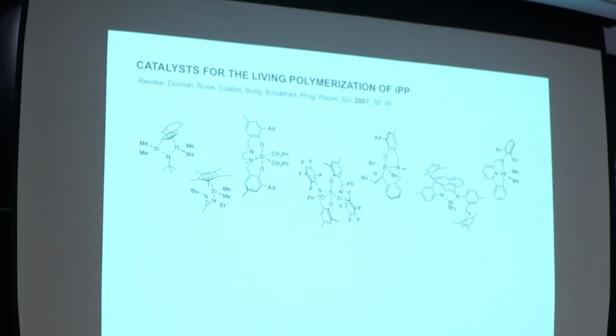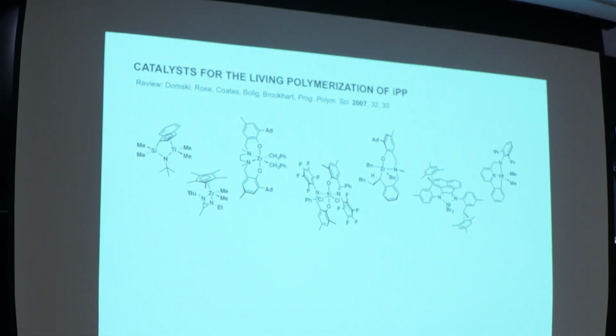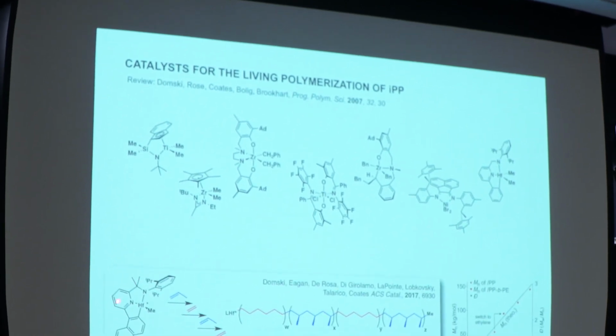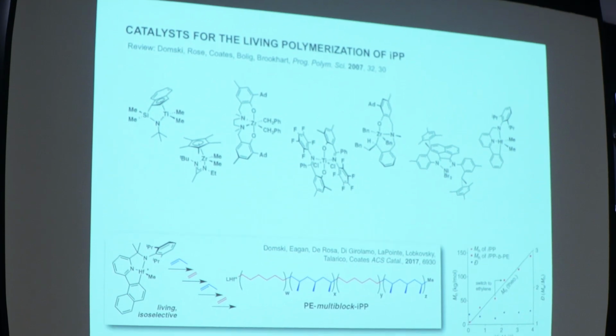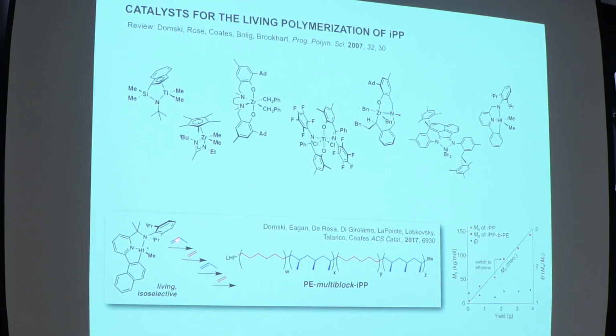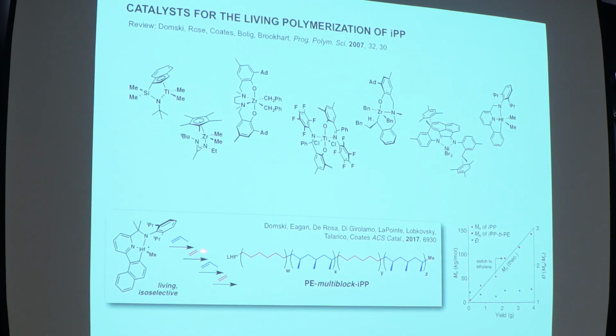Okay, so we decided to make these materials, and back to my catalyst background, we have developed a number of catalysts. These 4 on this side were catalysts that we've shown to be living and also make isotactic polypropylene. And what we wanted to do then is we made a modified version of the hafnium catalyst, which Tobin's done a lot of nice work with. In our case, we were able to first add propylene, grow a propylene block. We can then add ethylene. We can grow an ethylene block. And you can basically keep adding back and forth the two different monomers. And the catalyst will grow polymers over 500,000 in molecular weight. And you can control the block sizes by the amount of ethylene and propylene that you give it.